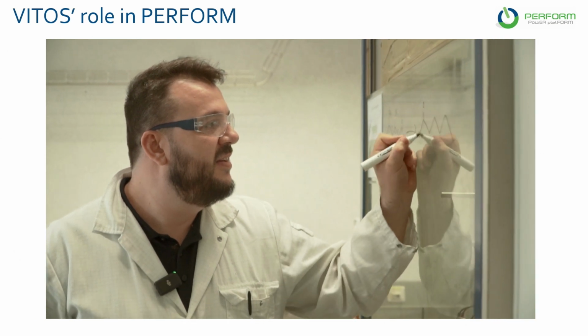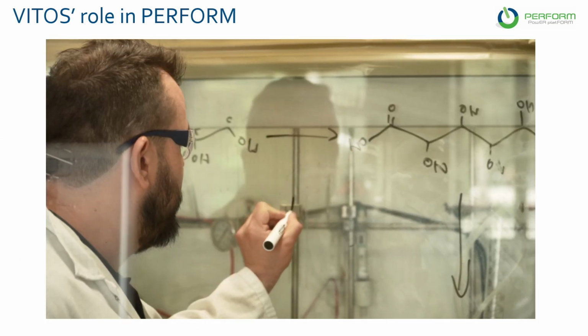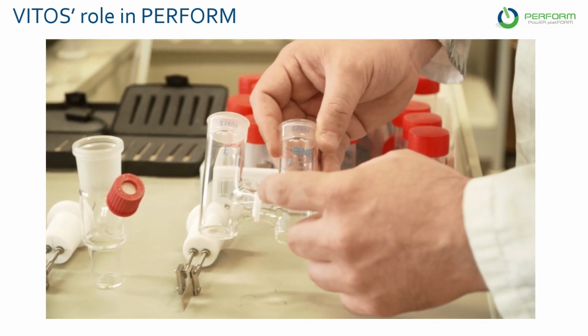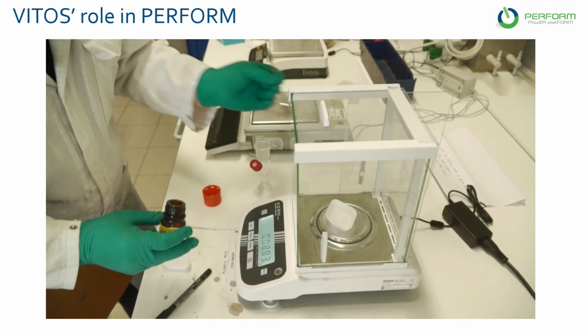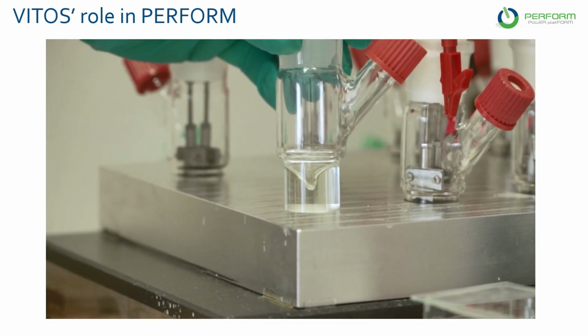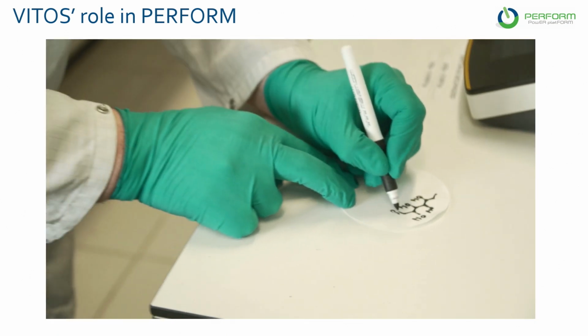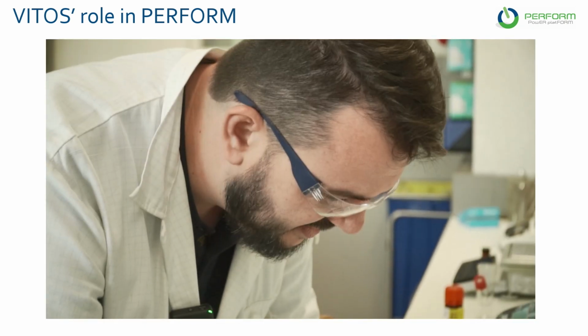So we will develop the electrochemical reaction in this process, but we will also focus on the DSP, the downstream processing so-called, which is the separation and the purification of the component that we form. Gluconic acid and glucaric acid are formed in our reactor and are separated by a process called electrodialysis. Electrodialysis actually selectively takes out glucaric acid and gluconic acid from our reaction mixture, and that's what we further will use for the separation and for the purification. This concentrate of gluconic and glucaric acid will then be transferred to a cooling crystallizer, and there we will drop the temperature, limiting the solubility of the glucaric acid and therefore creating precipitates and pure glucaric acid crystals.